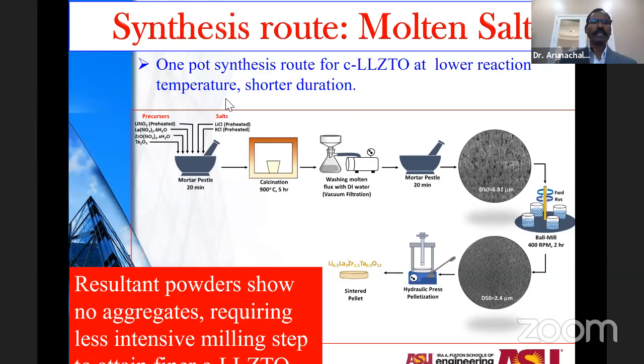So you can have a salt, which is a medium, lithium chloride and potassium chloride salt. That melts when the temperature of the precursors goes to 900 degrees Celsius. So the reactions happen with all the precursors in a liquid medium. That's a major advantage. And then, once it is taken out, you can disintegrate it, or you can wash it thoroughly with water. That washing has to be carefully done to avoid lithium exchange with the proton.